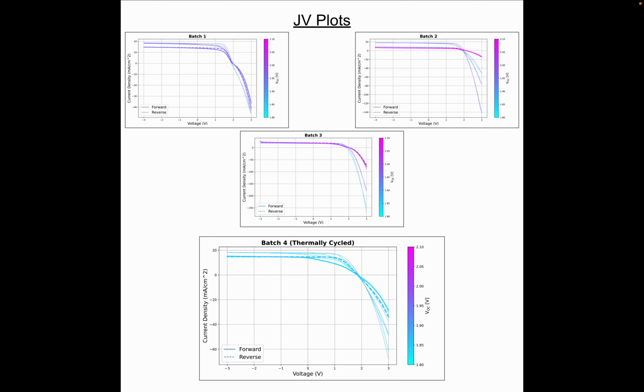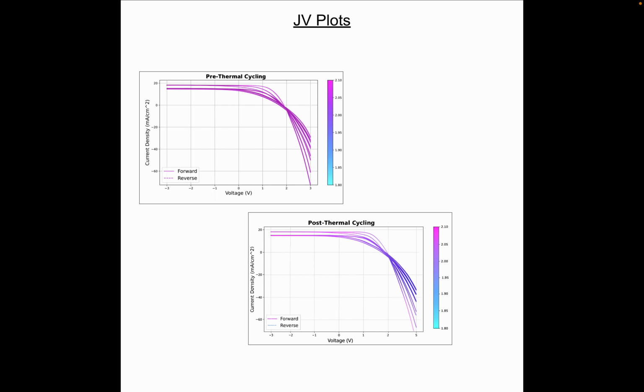And we noticed some minor issues in our batches when we did those rapid temperature fluctuations, that thermal cycling. But when it really gets interesting is when we looked at some of our updated batches. So we improved our devices, and we saw not only just internal improvement, but actually some very high VOC levels, both before and after thermal cycling when compared to our preliminary trials.